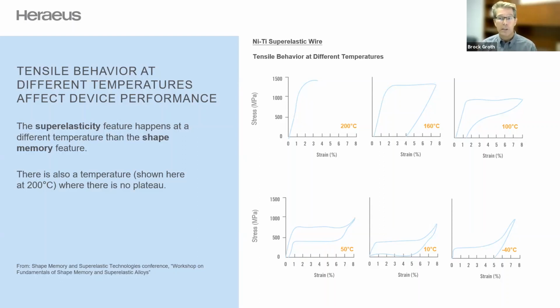So what we have here is the other example. So at 10 degrees C, this material still behaves superelastically. You pull it to 8%, it bounces back to 0, but the loading plateau and the unloading plateau are much lower than they were at 50 C. The material will feel, well, not only will it feel less stiff, it will be less stiff at that temperature. And if you increase the temperature, you basically go the other direction. At the higher temperatures, 160 degrees C, the loading plateau is very far up there.